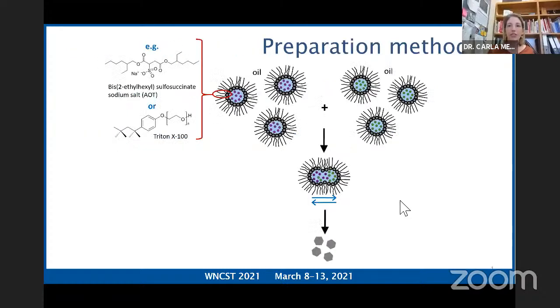So by way of introducing the microemulsion method that we use, this is just the basic approach that we use, and it can certainly get more complicated rapidly. First of all, we have a single three-phase microemulsion system where we have an oil-based continuous phase, a surfactant that forms the reverse micelles, within which we have some polar phase. And that polar phase is then used to dissolve the reactant. So it might be the ligand, for instance, here, and a separate microemulsion within which we dissolve the metal salt.